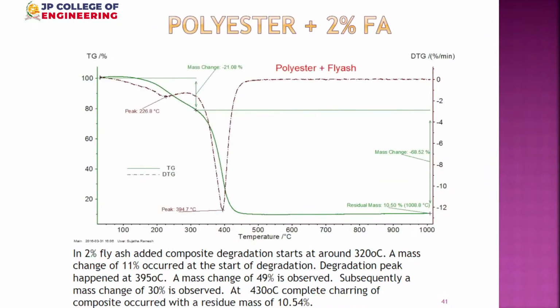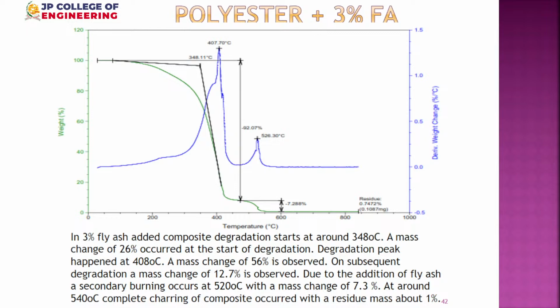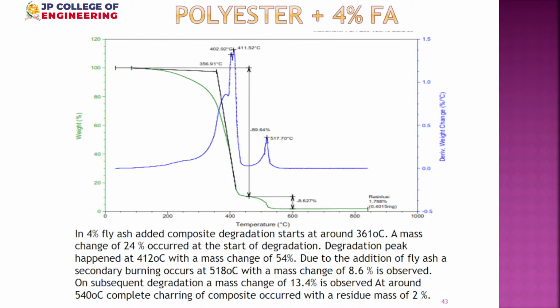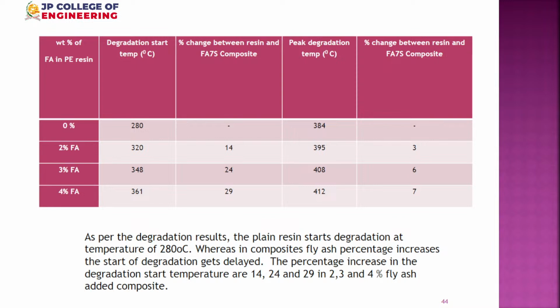For 2%, you can see that the degradation starts at 320, compared to 280 for our plain resin. Peak degradation is at 395, and almost at 430 the degradation is completed. Next slide, please. For 3%, the degradation started at 348, peak at 408, and like this. Now go to the next slide, where it summarizes all the findings.